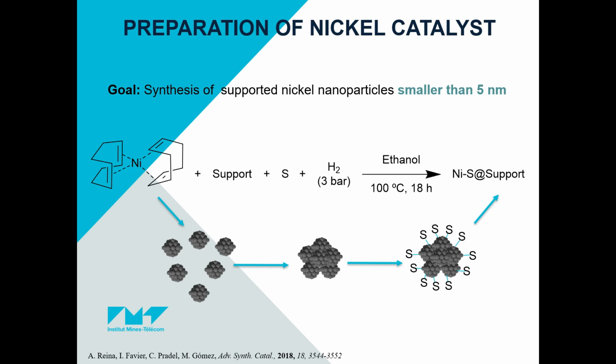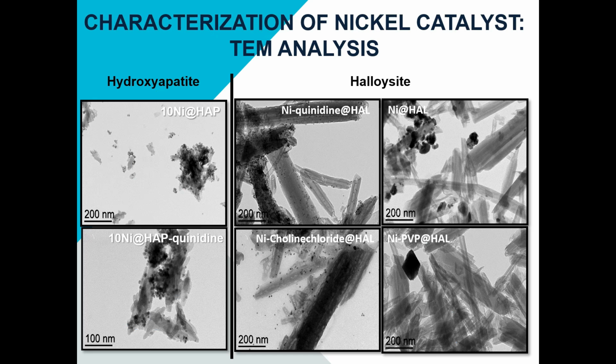Two support-based families of materials have been prepared so far. One based on hydroxyapatite, a calcium phosphate mineral, and another one based on halloysite, a nanoclay. With the halloysite-based materials, a screening of different stabilizers, steric, electrostatic, a ligand, and the same support without any additional stabilizer was performed, arriving at the conclusion that the ligand, quinidine in this case, was the best stabilizer.